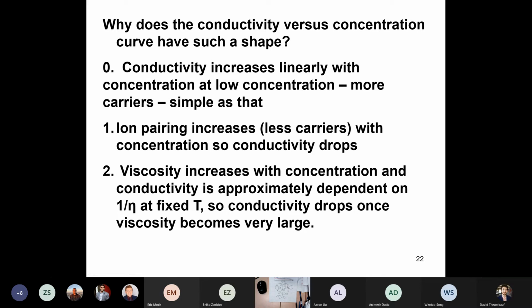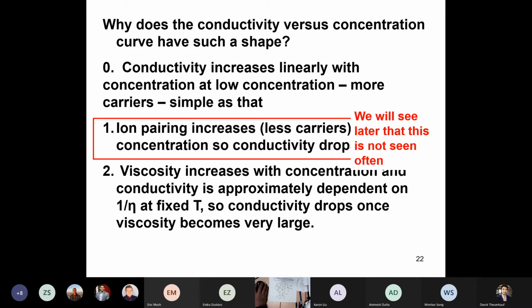Now what Eric showed, which I think surprised a lot of people in the lithium battery field, is that this ion pairing is not a very big deal, even up to 4 molar concentration in typical electrolytes that we work on. So we'll see later on that this is not often seen in the electrolytes that we see, and all of the conductivity drop with concentration comes about from viscosity increase. Okay.